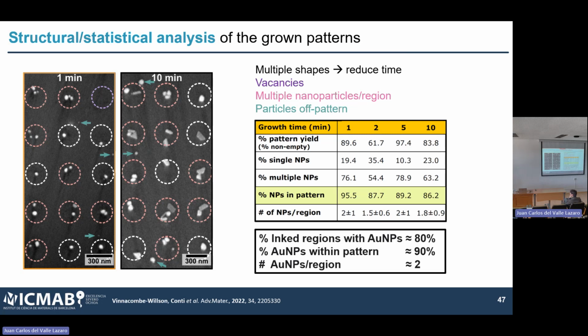The first one is that for the moment, we didn't do anything to control the quality of the particle that we're growing. So the system has been just optimized for not having secondary nucleation. And that was really the turning point. We have worked on this for about 7 months, and we were not getting any kind of pattern. And then once we managed to avoid secondary nucleation, the pattern emerged. And so the one thing to keep in mind is that there is a lot of work to do to make the particle better and more uniform.